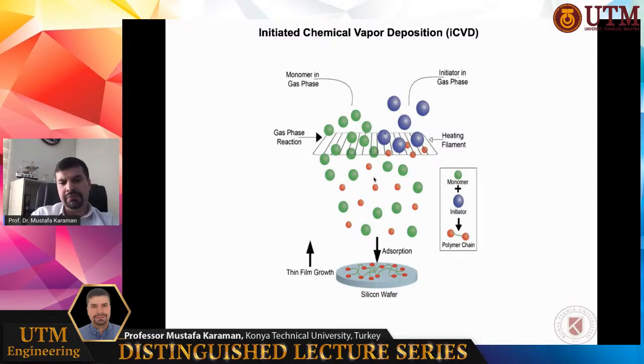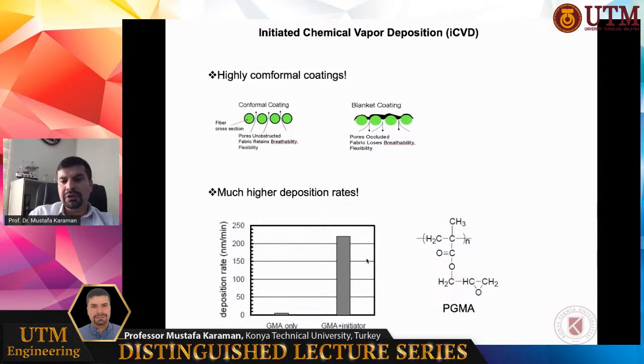The initiator molecules are dissociated and diffuse to the substrate surface, where they react with the adsorbed molecules to start a fast polymerization reaction. So, in this way, you can have a highly conformal polymer coating at very high speeds. This is the basic advantage. By conformality, I mean that geometrically complex substrates are coated uniformly.